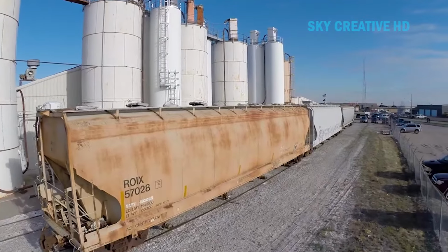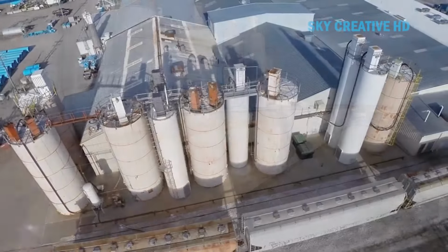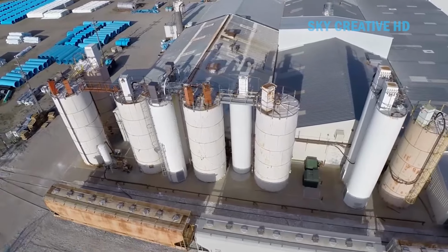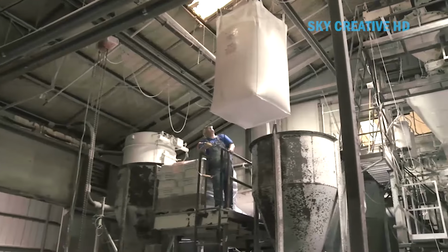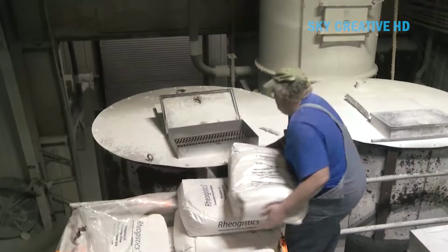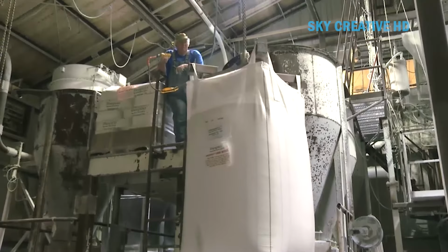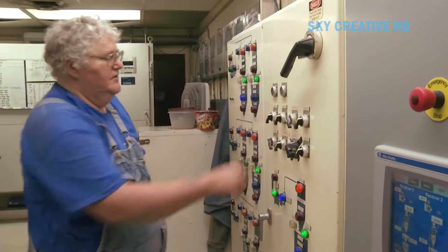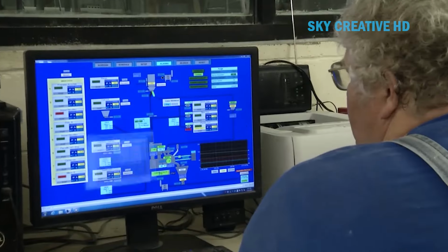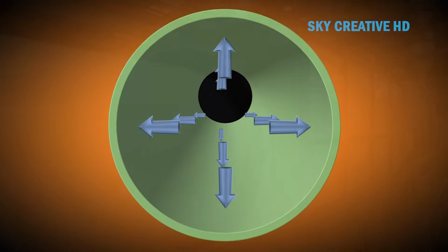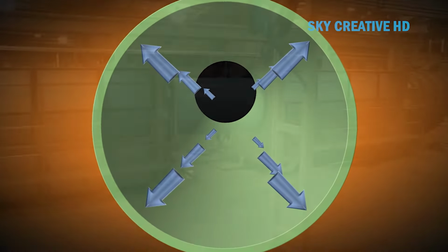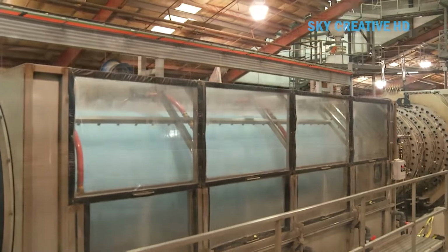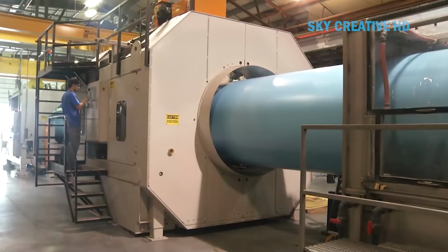Welcome to Diamond Plastics Corporation, where they've been revolutionizing pipeline technology since 1982. Now, if you remember when most pipes were made of cast iron or clay, you'll appreciate how PVC transformed infrastructure: lighter, longer lasting, and immune to corrosion. This operation produces massive 54-inch diameter PVC pipes using a process called continuous extrusion. It starts at the material handling system, where polyvinyl chloride resin arrives in pellet form. These aren't just any pellets. They're compounded with heat stabilizers, impact modifiers, and processing aids that give the pipe its legendary durability. Automated systems blend these ingredients in precise ratios, typically around 3% additives to 97% PVC resin.